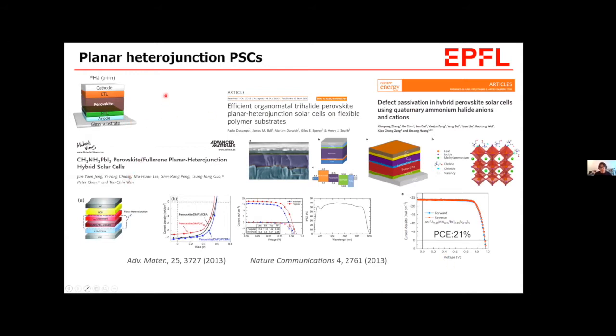And here I show the other stack, PIN planar heterojunction, which was first developed in 2013. They brought the structural concept from organic solar cells first. So they used this concept of donor and acceptor. Although the efficiency was much lower compared to the mesoscopic devices at that time, this work had the significant meaning in developing a new design for perovskite solar cells that could be processed at low temperature, like 150 degrees C.